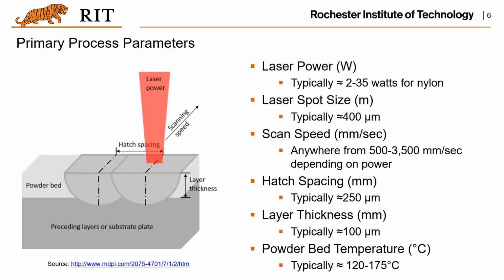Since it's also a laser-based process, it has similar parameters. First is the laser power and also the spot size, scanning speed, which is quite similar to stereolithography, right? And there is the hatch spacing. So basically it represents the spacing between different scanned tracks, right? And layer thickness.